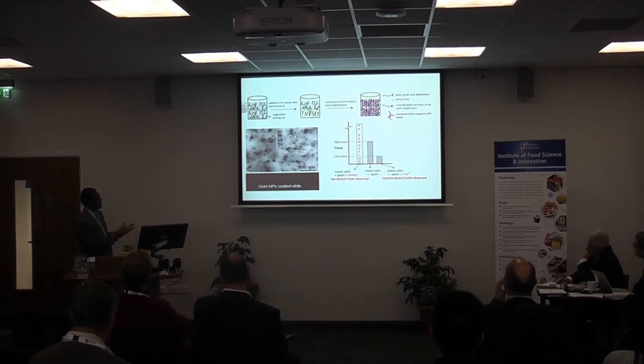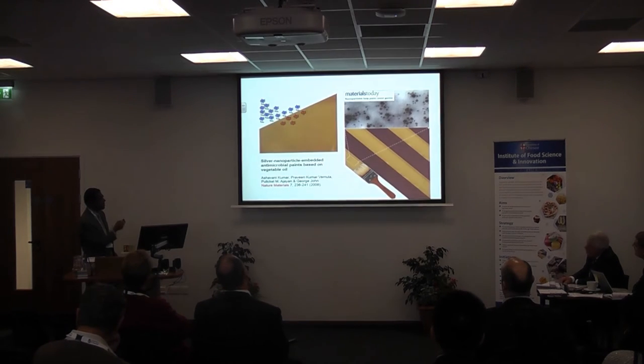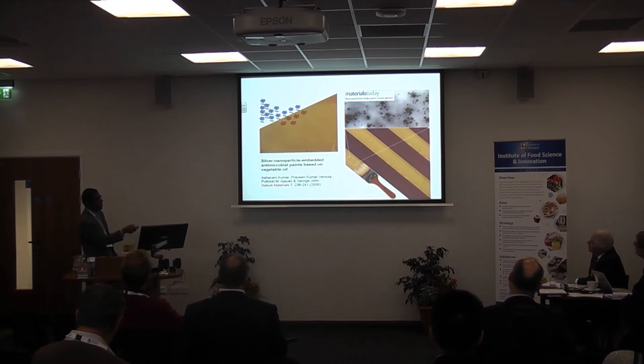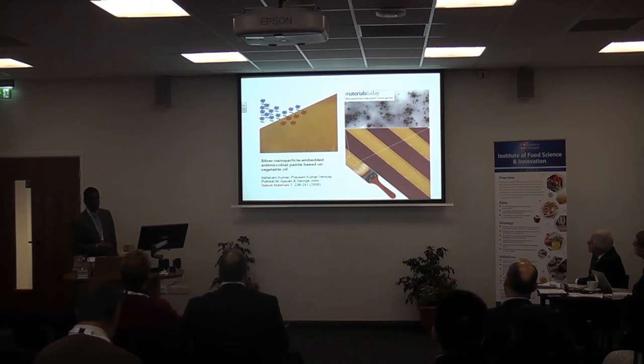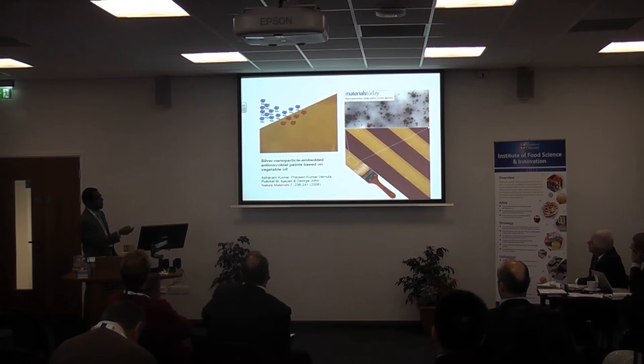These are metallic nanoparticles. Our interest was to demonstrate that this chemistry is useful for creating something in the laboratory, but we found it was much more interesting. We create nanoparticles in the vegetable oil, utilizing nature's chemistry of oxidation. We create paints. This is a paint from vegetable oil containing gold nanoparticles. This is a paint we created in the laboratory which contains silver nanoparticles, about 20 nanometers in size. And this silver-containing vegetable oil paint is a beautiful paint.